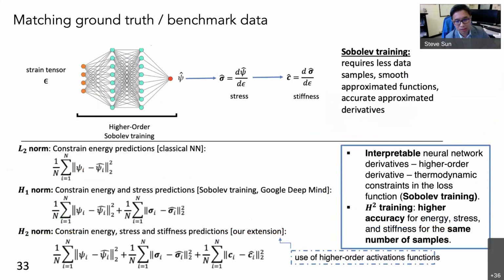So for the elastic part, we can generate the constitutive law by training an energy functional. Here the idea is that instead of generating a supervised learning that links the strain to the stress, we try to create a richer label by using the energy, the stress, and the stiffness all as outputs. And we actually have this data in the experiment. We're just not using it in the classical machine learning training.